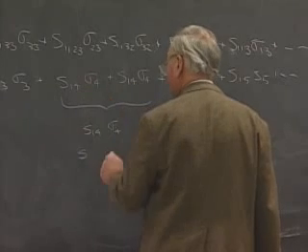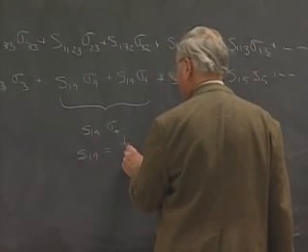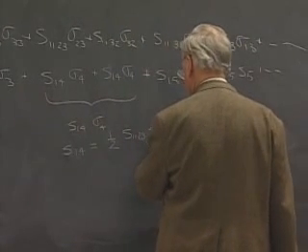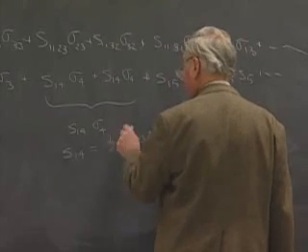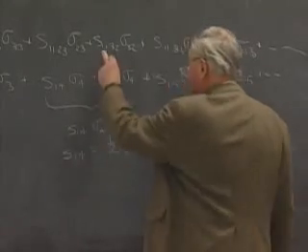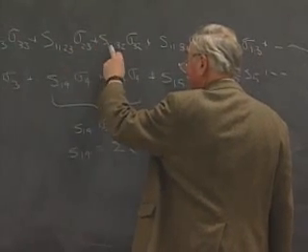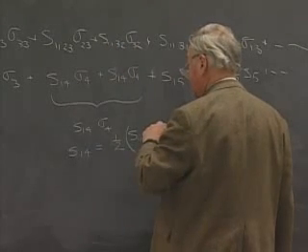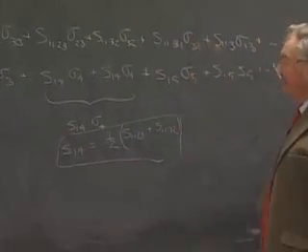And in so doing, we have to combine the factor of 2 into the definition of S14. So S14 would be equal to 1/2 of S1123 plus S1132. So it's going to be half of one of these equal terms that involve one on-diagonal subscript and one off-diagonal subscript. So this is the only way we're going to be able to write a nice, clean matrix representation.